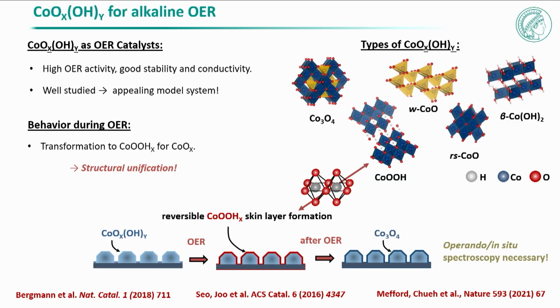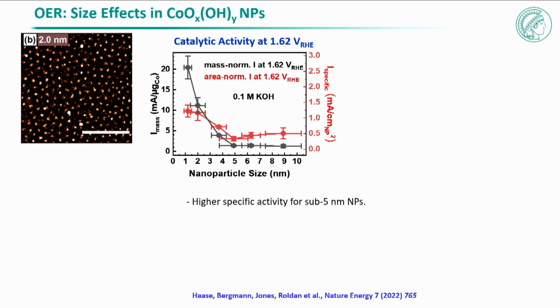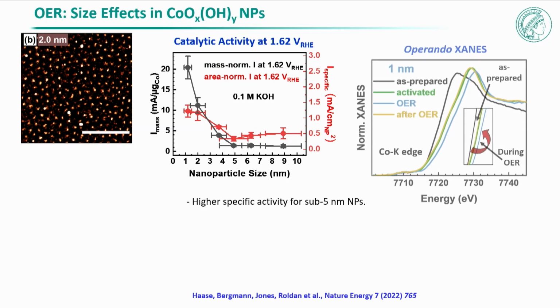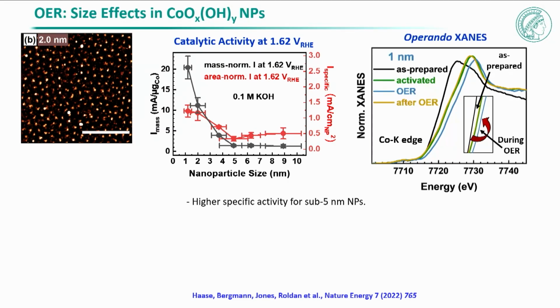Then this requires operando spectroscopy and microscopy. If you are thinking about what are the things that we can look at, we need to make the material more efficient, and we need to make the material more durable. And to do that, you can think, for example, about designing the pre-catalyst with different sizes. So we did this. We were looking at different cobalt oxide and cobalt hydroxide catalysts with different particle sizes. And when you decrease the particle size and you are below a certain regime, like 5 nanometers, you see that it's more active. So we can now understand more why this is more active.